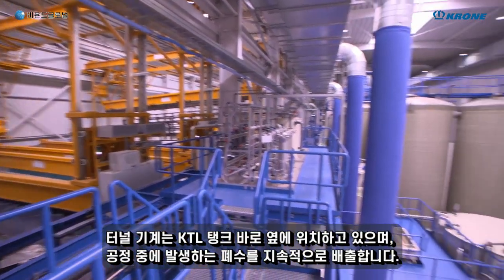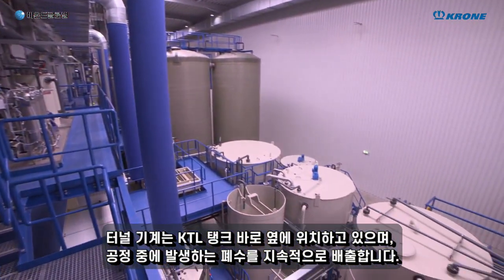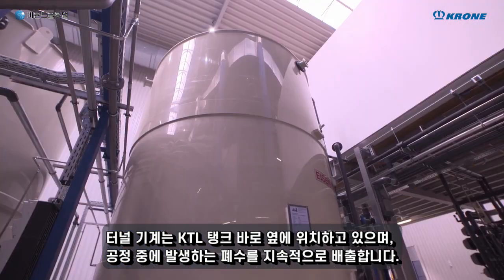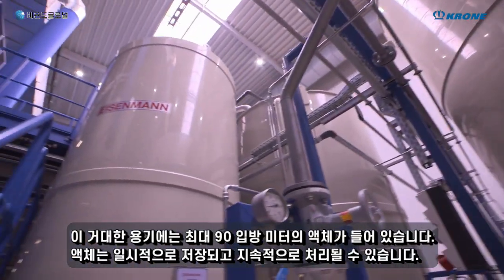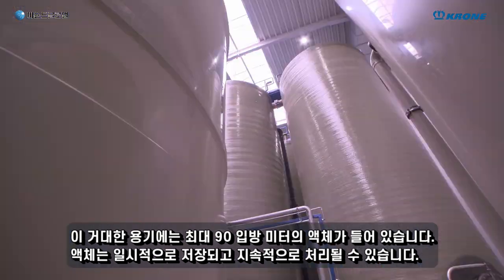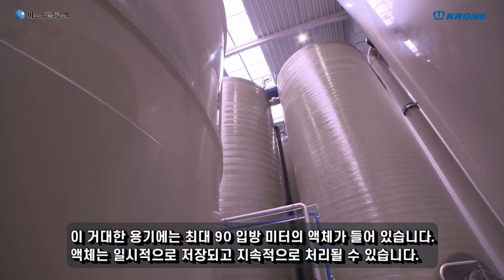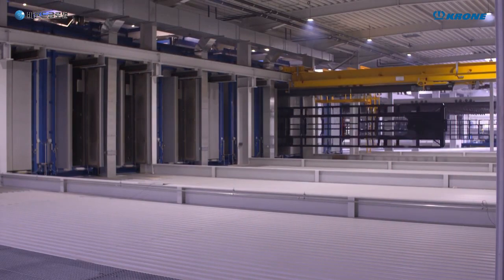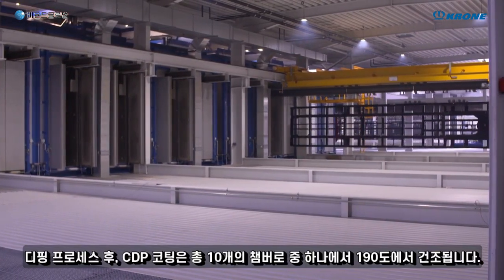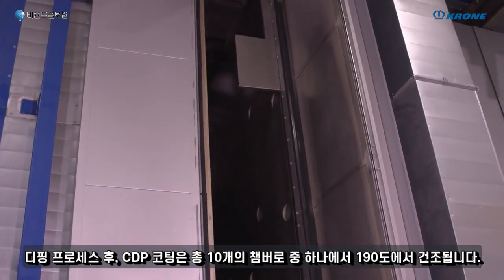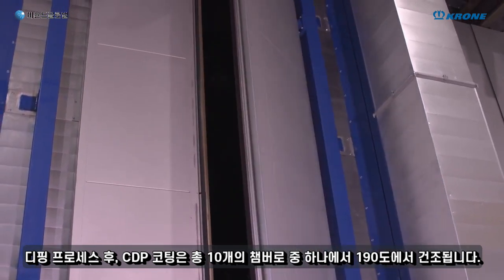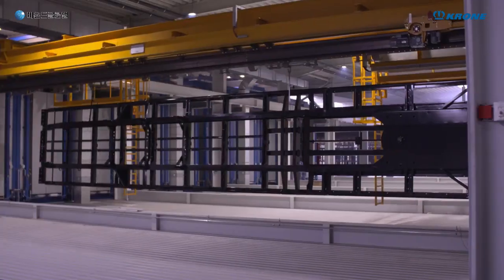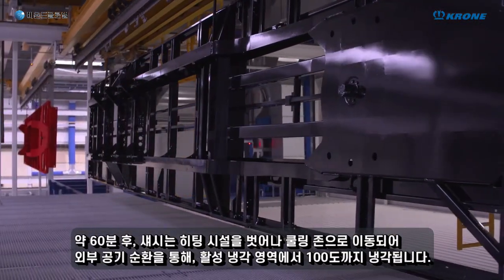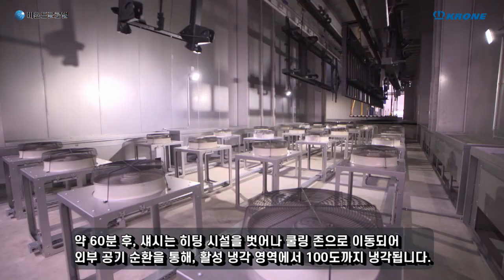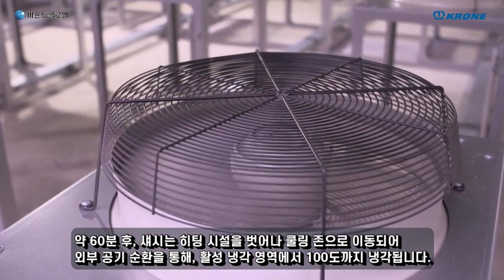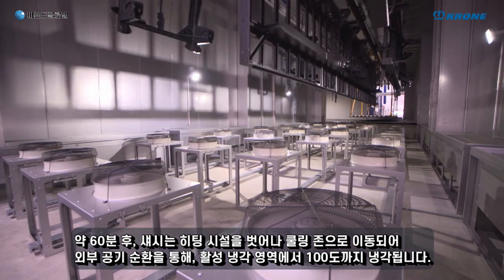The tunnel machine is located directly beside the CDP bath to continuously treat the wastewater generated during the process. The massive vessels contain up to 90 cubic meters of liquid, which can be temporarily stored and continuously treated. After the dipping process, the CDP coating is then fired in one of a total of 10 chamber furnaces at 190 degrees. After about 60 minutes, the chassis leaves the furnace and is cooled down to 100 degrees in an active cooling zone using external air circulation.